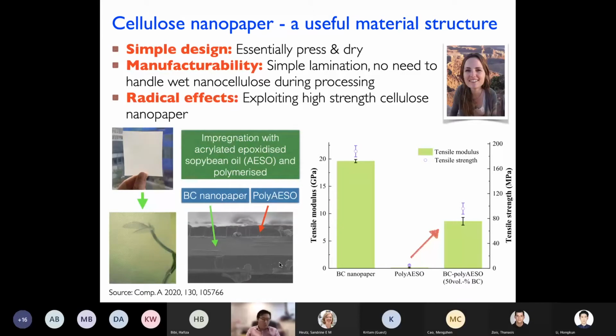What is more interesting here is that the nanopaper alone, the consolidated paper made out of nanocellulose, the dried ones, has a tensile modulus of approximately 20 gigapascal. So not as high as the 165 gigapascal single fiber value, but the 20 gigapascal actually stems from the 165 gigapascal of the single fiber there. And this nanopaper actually has a strength of approximately 180, 190 megapascal there. Your polymerized soybean oil is a very weak and soft polymer matrix. Just by introducing this nanopaper at 40%, 50% volume fraction, you're able to push the performance up to about 7.5 gigapascal in modulus, approximately 100 megapascal in strength.